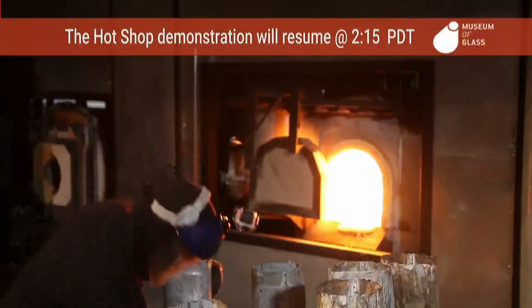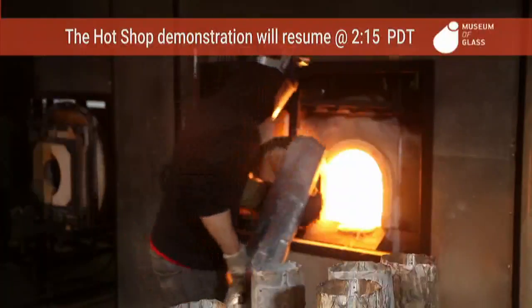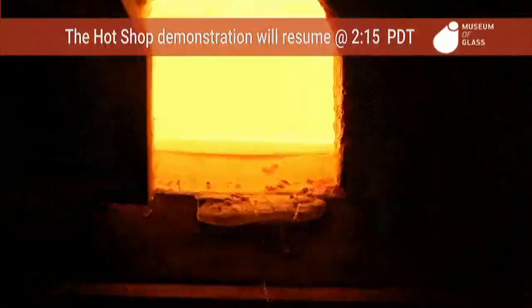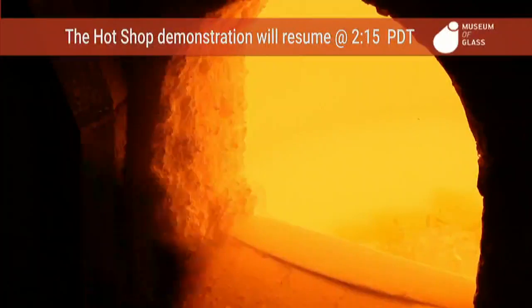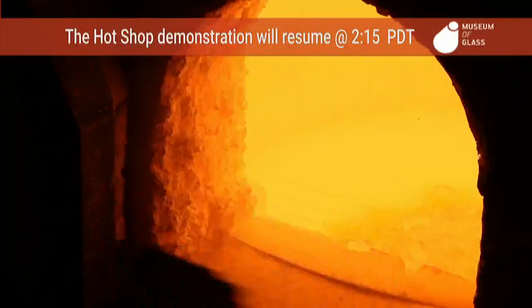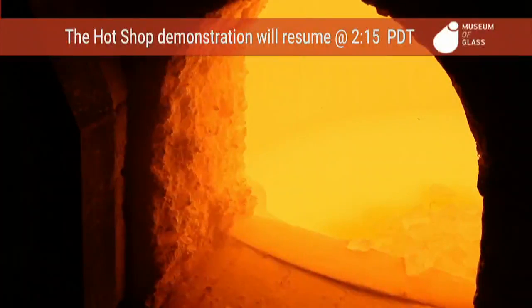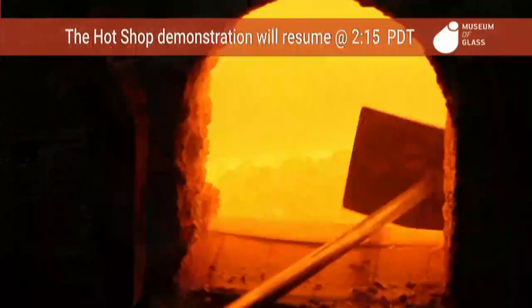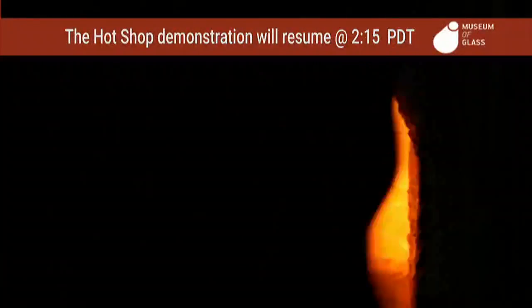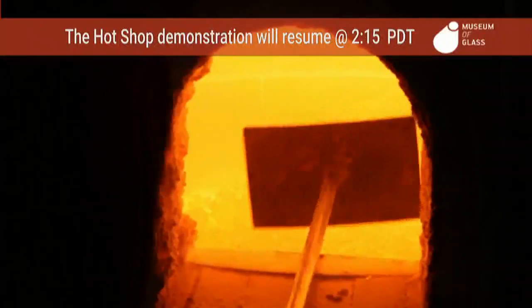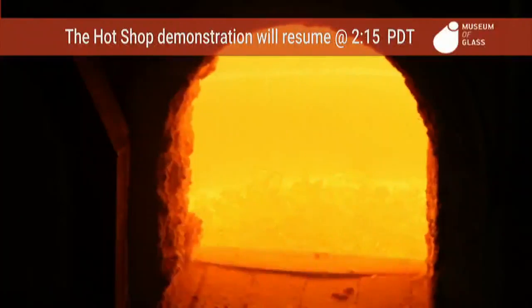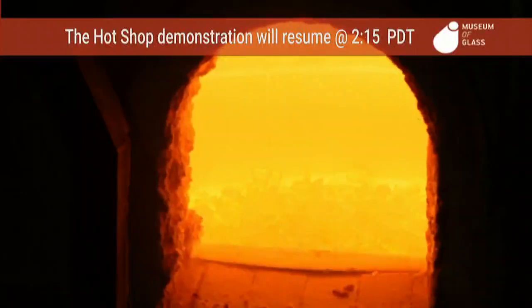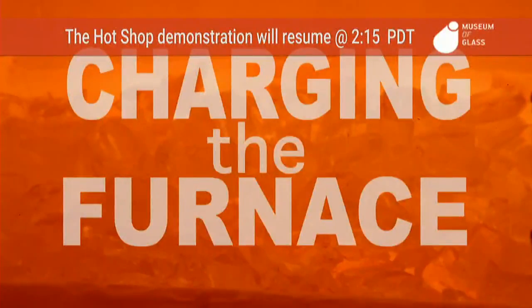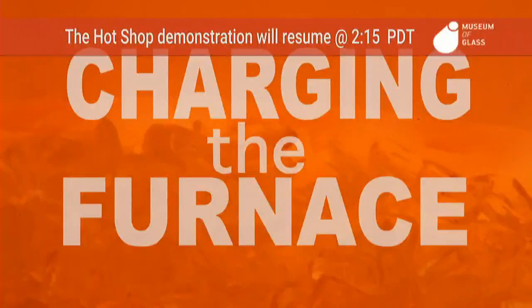The primary ingredient in glass is silica sand, or silicon dioxide. The other 2 main ingredients are soda, or sodium oxide, which lowers the melting temperature, and lime, or calcium oxide, the stabilizer. Once the cullet is loaded into the 2300 degree furnace, a rake is used to level the glass for even melting. The furnaces at the Museum of Glass hold approximately 1,000 pounds of clear molten glass and run continuously 24 hours a day, 7 days a week.